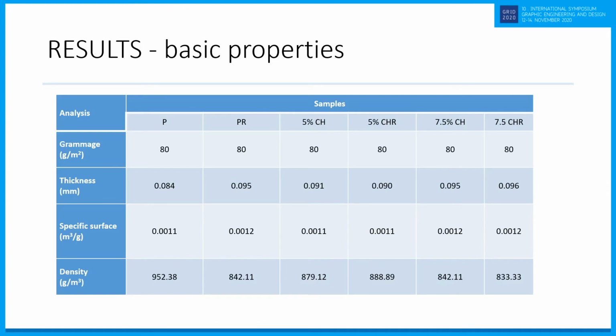To evaluate the influence and effect of bio-based components on paper, it was essential to prepare samples with the same grammage. Therefore, the paper sheets were prepared with a grammage of 80 grams per square meter. The beating degree of the pulped hardwood fibers, dimensions of the fibers, and addition of the fillers influence the thickness of the paper, and this plays an important role in end usage, especially for printing papers like ours.